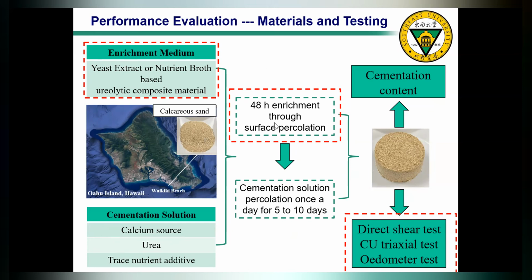For the first 48 hours, the enrichment medium was percolated through the surface of the soil sample to stimulate the growth of the native bacteria. 48 hours is the optimized time we found, and the concentration of urea within the enrichment medium is 170 mM. Then after 48 hours, we percolated the cementation solution once a day for 5 to 10 days. The aim of this percolation is to generate biocementation at different levels. The longer the period of percolation we perform, the higher the cementation level we expect.